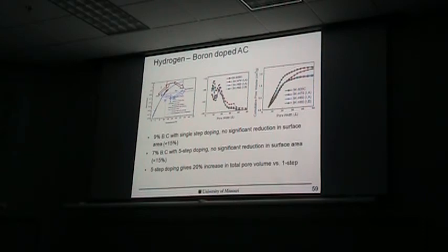We reached a 7% boron to carbon ratio with a 5-step doping, which has almost no effect on the surface area. But with the multi-step doping, you see it over here, this is the red curve, you end up with more pore volume compared to the single steps. The black curve is the precursor, this is just the activated carbon.